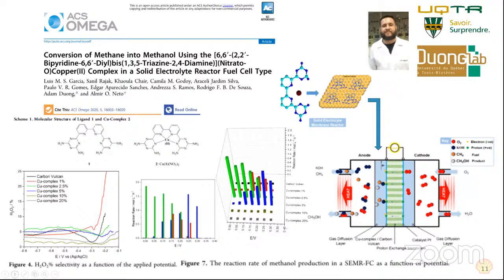And the test of the complex synthesized with copper as the metal proved to be efficient in converting methane into methanol. And the most active material for methanol production has about 5 or 6% selectivity for hydrogen peroxide in indirect water activation tests using RRDE, as previously presented.